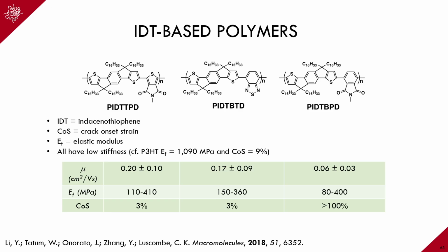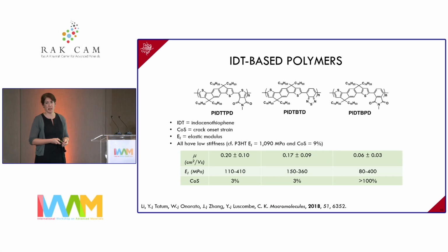Again, because normally semiconducting polymers are brittle, the elastic moduli that we measure are typically in the 1 gigapascal regime. But these polymers were showing an order of magnitude lower elastic modulus, showing that they were less stiff, confirming the amorphous nature that people were seeing using X-ray spectroscopy. But there is one other number that we looked at, and this is the crack onset strain. So here, you make a thin film, you pull the film, and you just visually watch when the film starts to crack. And in 2 of them, it cracked straight away. But that squishy one that I told you about earlier was stretching a lot more.